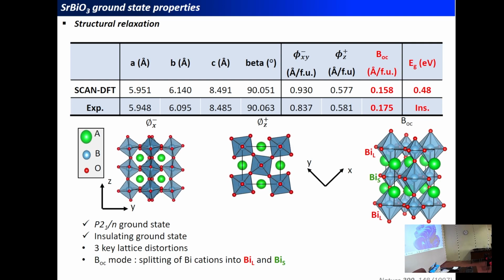And so this ground state is characterized by 3 key lattice distortions. We have 2 octahedral rotations: one antiphase octahedral rotation in which the BiO6 groups are rotating in antiphase along the x-axis, and the same one along the y-axis, and one in-phase rotation along the c-axis. But the most important feature in this material is the presence of what I call the breathing distortion, which is producing a rock salt pattern of large octahedra, which are surrounded by compressed octahedra. And so it's splitting the bismuth cation sites into 2 different environments. One bismuth cation that I will call bismuth L, for large, is sitting in an extended octahedron, and all the surrounding bismuth cations are sitting in compressed octahedra.